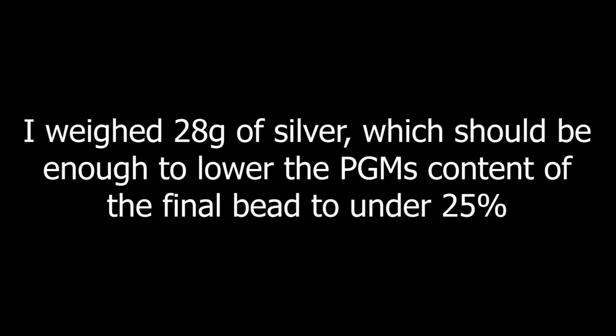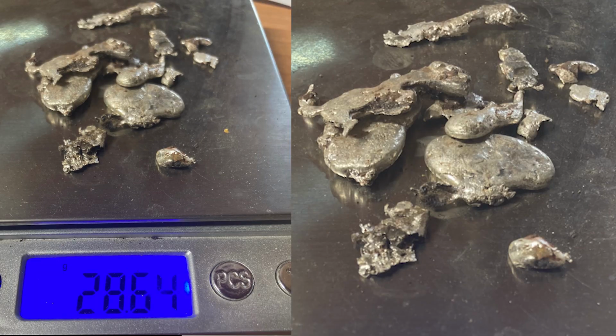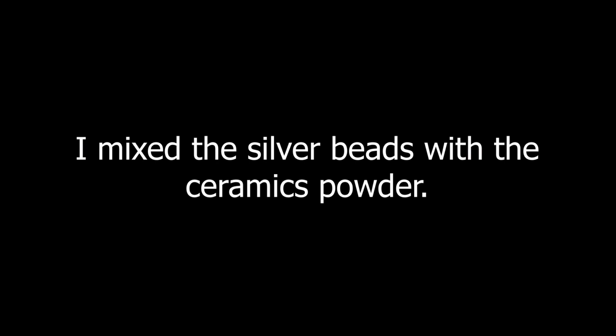I weighed 28 grams of silver, which should be enough to lower the PGM's content of the final bead to under 25%. I mixed the silver beads with the ceramics powder.